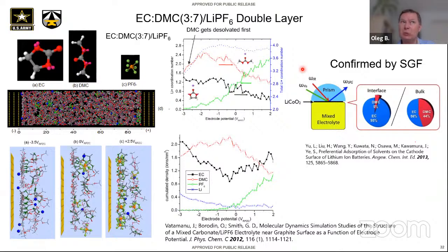How would a LiF passivated cathode differ, I mean, what's the difference in that double layer versus the double layer on just graphite? I can tell you one thing, we did look at lithium iron phosphate previously. And of course, what you see there is that the carbonyl group binds to the transition metal, and then for EC, the other, it's in the opposite direction with the ethylene group going towards the oxygens, right? So you have exactly this type of opposite dipoles, one against another. And there are similarities to what happens here, right?